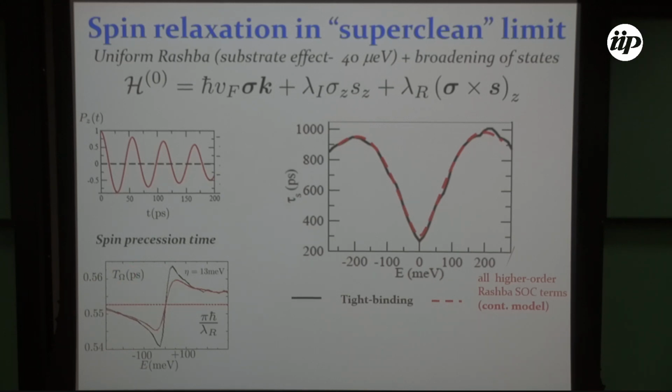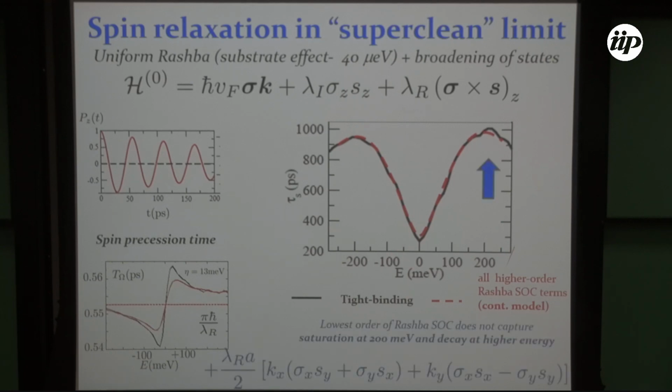That's the key difference, which is unveiling all the entanglement reflected in the dynamics, and which explains the minimum at the Dirac point. Actually, we also found something, and for a time nobody could measure it: there was a downturn at high energy where pseudospin entanglement was lower. But we found that if you look into your low-energy spin-orbit coupling Hamiltonian and you add extra higher-order terms, then this downturn is found.